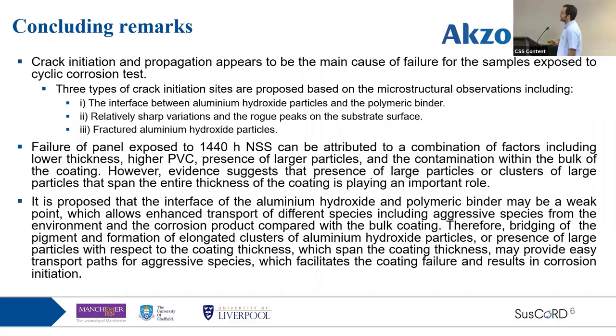And finally, to conclude, crack initiation and propagation appears to be the main cause of failure for the samples exposed to the cyclic corrosion test. Three main initiation sites are proposed, which are at the interface of the aluminium hydroxide particles with the polymeric binder, fractured particles within the coating, and the rough surface variations on the substrate. Also, failure of panels exposed to the neutral salt spray test can be attributed to a combination of factors, including lower thickness, higher PVC, presence of larger particles, and contaminations within the bulk of the coating. However, evidence suggested that the presence of large particles or clusters of large particles that span the entire thickness of the coating plays an important role.